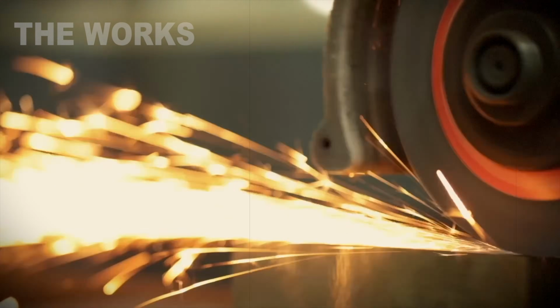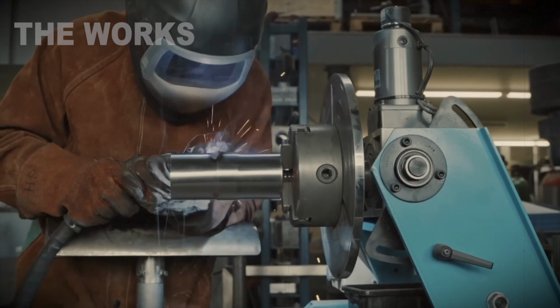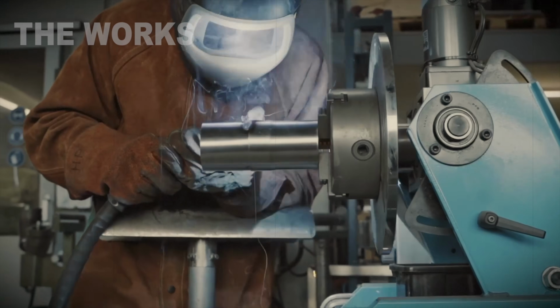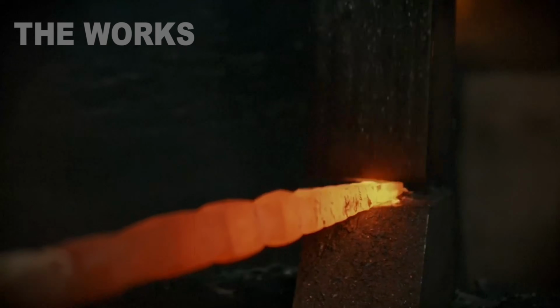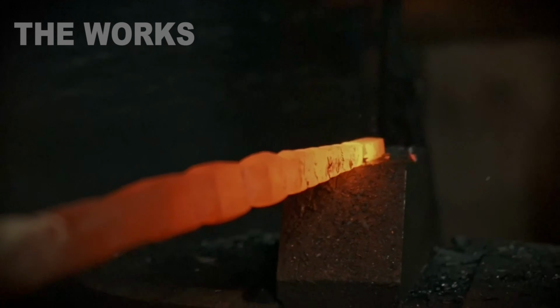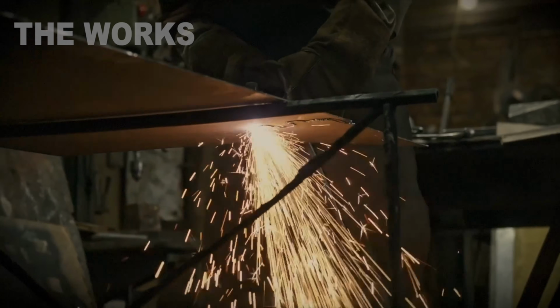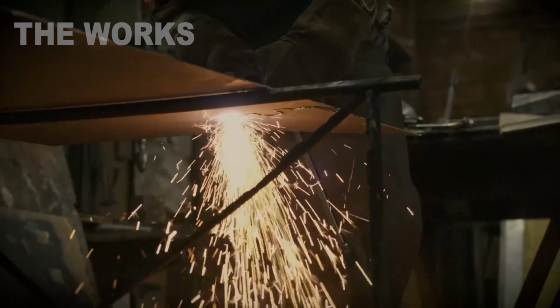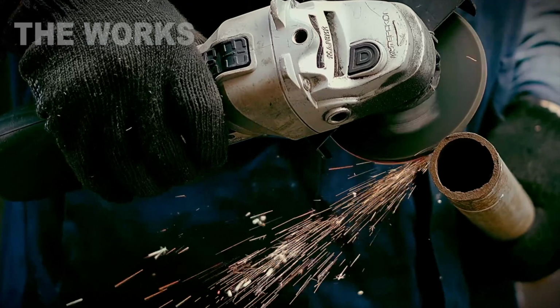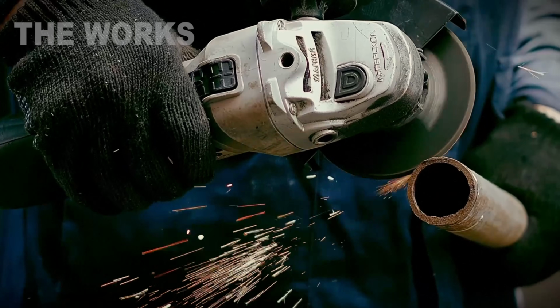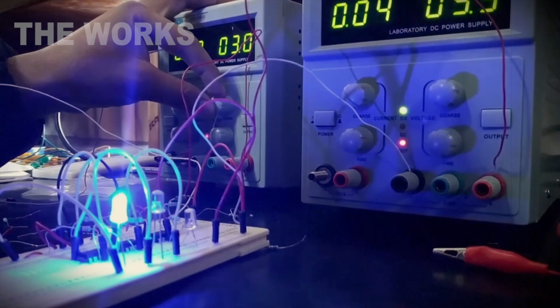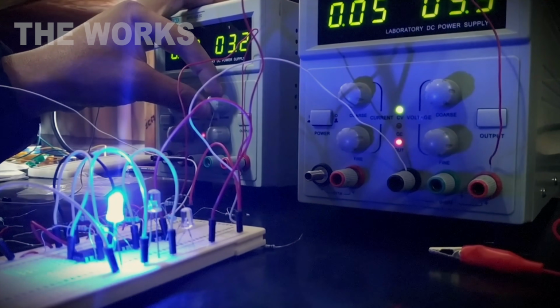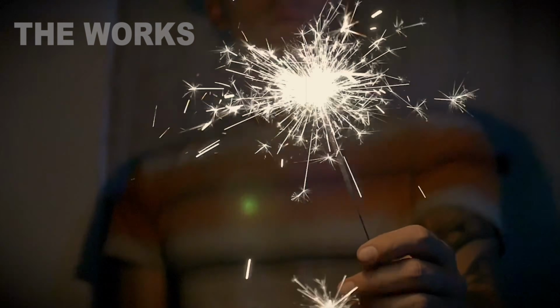Titanium parts, the sail, fairings, also separate. Titanium doesn't melt with steel. Different melting points. Titanium, 3,034 degrees Fahrenheit. Steel, 2,795. Copper alloys, wiring, heat exchangers, to non-ferrous metal. Aluminum alloys, bulkheads, ladders, to aluminum scrap.